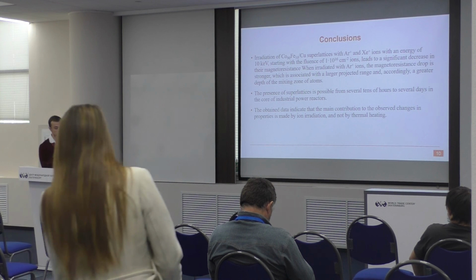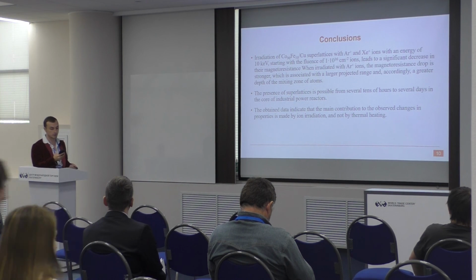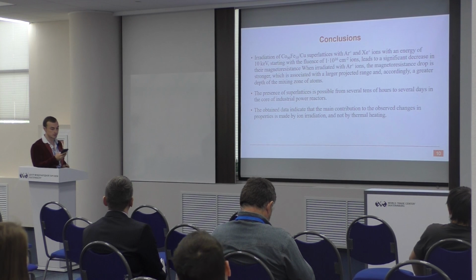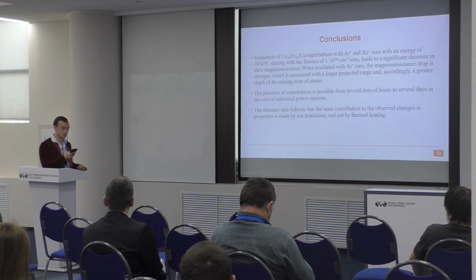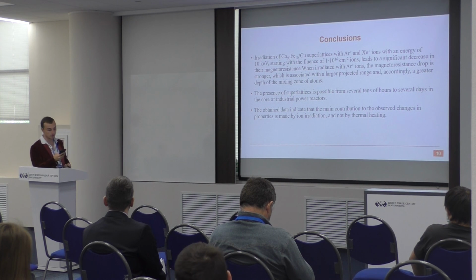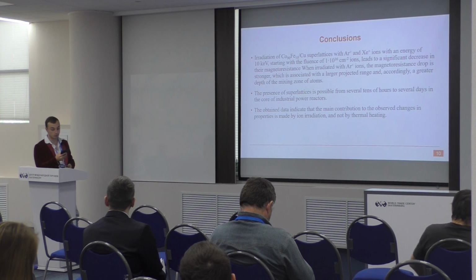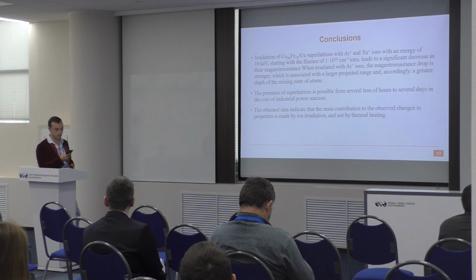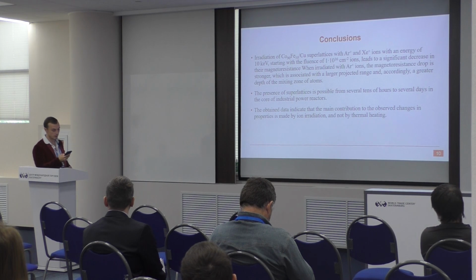Thus, it is established that radiation with argon and xenon ions with an energy of 10 keV of superlattices, starting with the fluence of 10 to the 16 centimeters to the minus second degree, leads to a significant decrease in their magnetoresistance. With radiation by argon ions, the magnetoresistance drop is stronger, which is probably due to a larger average projected range and accordingly a greater depth of the mixing zone of atoms in the direction from the film surface to the substrate than for xenon ions.